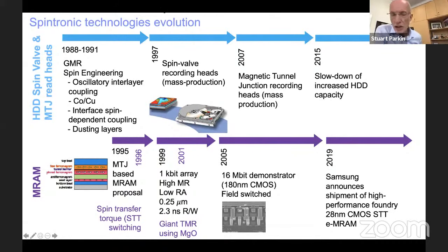As I said, in 2007, the basic physics switched from spin-dependent scattering, giant magnetoresistance, to spin-dependent tunneling, but the essential spin-engineered structure remained the same. Now today, in magnetic disk drives, the evolution has slowed down considerably, and we need to do something else. And partly this is because the magnetic disk drive is innately a two-dimensional technology where you store information in magnetic bits in a single magnetic film. I want to compare that with magnetic random access memory, MRAM, where you use essentially a similar magnetic tunneling junction designed to have slightly different properties.